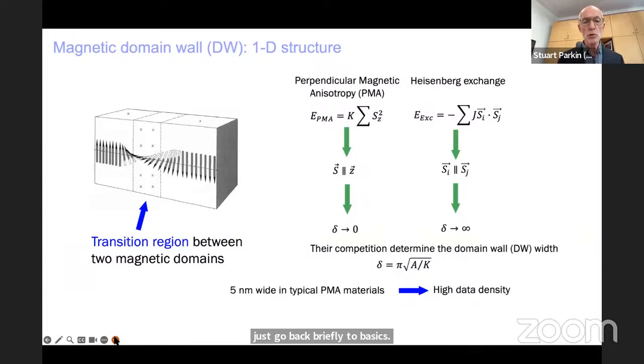And if you look at magnetic domain walls, in particular in materials with large uniaxial anisotropy, and in thin films, this is often a perpendicular magnetic anisotropy, then the magnetic moments in a ferromagnetic system are coupled through a Heisenberg exchange. And yet, at the same time, there can be domains and domain walls. And the domain walls have a characteristic length scale, which is determined by competition between the Heisenberg exchange and the anisotropy. And when you have typical thin film heterostructures that I'm going to introduce, in particular formed from ultra-thin layers of cobalt and nickel, the interfaces give rise to a significant perpendicular magnetic anisotropy, so that the typical length scale, or the width of such a domain wall, would be of the order of 5 nanometers.